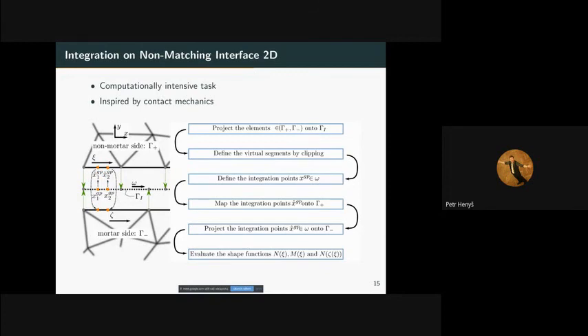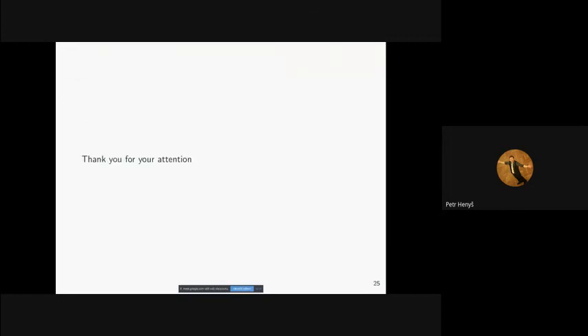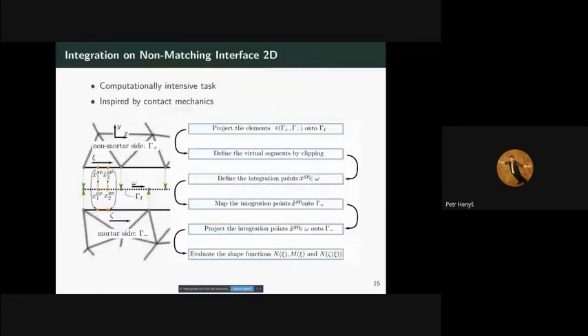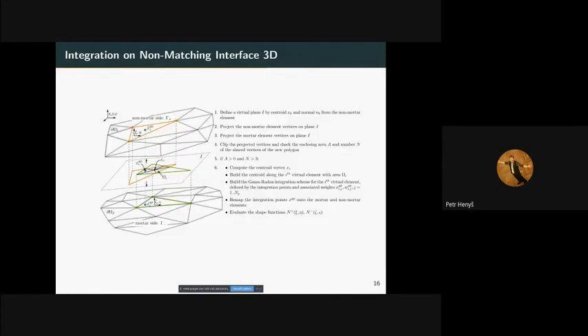Which is actually what we usually need if we are trying to find a new integration scheme, for example. Well, in 2D, it's quite easy. You can use many tricks from computational geometry, but in 3D, it's much more challenging, because now you don't work with just a simple edge, which you can simply segment, right? You can make more segments from that, but now you have an intermediate surface, and this surface contains an object, which is basically a projection of one element from one side to the second element from the other side. And then you need to find the intersection, right?